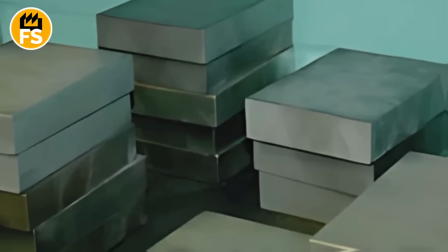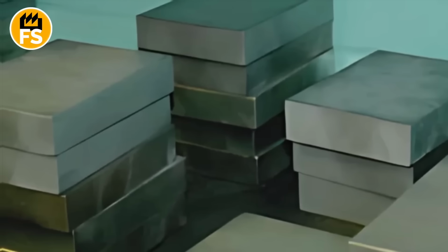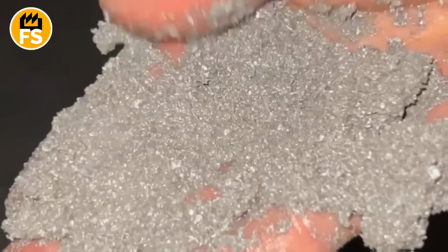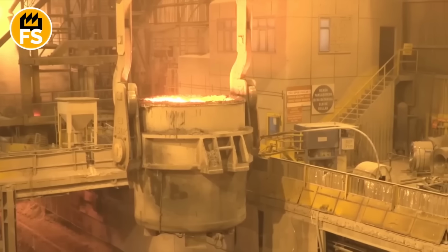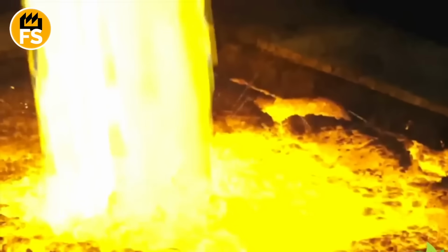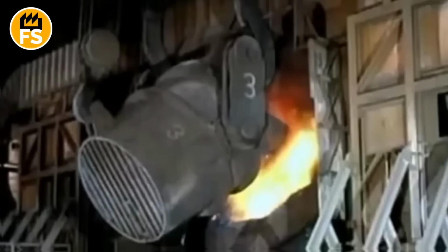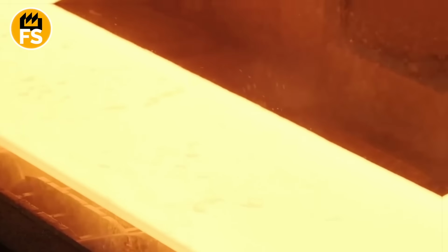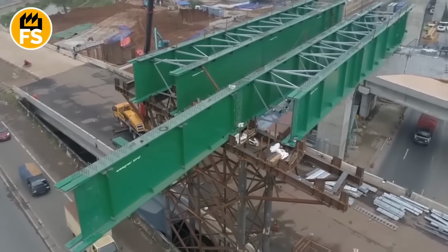As it cools, the ferrovanadium crystallizes, forming solid ingots or granules with a characteristic dark gray surface. The material is then crushed to a convenient size, packaged, and shipped to steel mills. The main value of ferrovanadium lies in its predictable behavior in molten steel. It dissolves quickly, is barely lost during melting, and allows precise control over microalloying. That's exactly why ferrovanadium became the standard form of vanadium supply for producing high-strength steels, from building structures to automotive components and armored products.